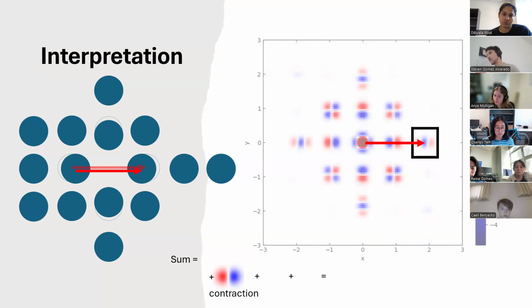Okay, so that interatomic distance is shortening. And then we also have this pair where that interatomic distance is increasing, right? And the interesting thing is that even though those two seem like opposites, they're not equal in magnitude. And because we can resolve the positions in the delta PDF space, we also realize that these two dipoles are not actually perfectly overlapped, okay?